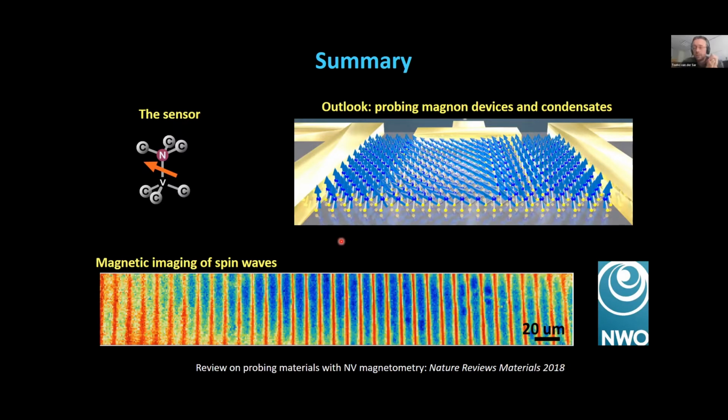I think I know what you refer to. So with the NV center, it's important that you apply the static magnetic field along its axis. So there have been measurements at 10 Tesla already with 200 gigahertz ESR frequency. It's just a spin, you know, in the end. There's nothing strange there. But if you apply a field perpendicular to its axis, the spin-dependent photoluminescence quenches. So then you cannot use it.